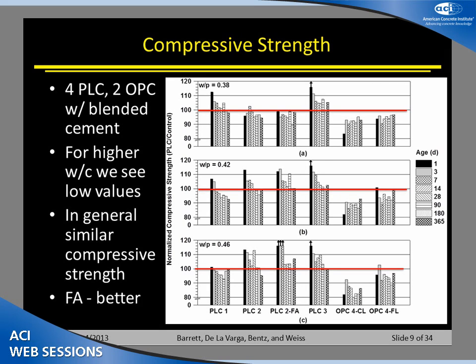And one of the things that we can notice very quickly when we're looking at compressive strength with these commercial Portland limestone cements, commercial clinker, all of these give you really similar performance to what you see with the conventional OPC. We're within 95% of the strength, typically across the board. Sometimes we see a slightly higher strength at early ages. Reason for this is because of the finer grinding. By the time we get out to later ages, we're usually hitting about equivalent performance at 28 days and maybe something slightly lower at long-term values.